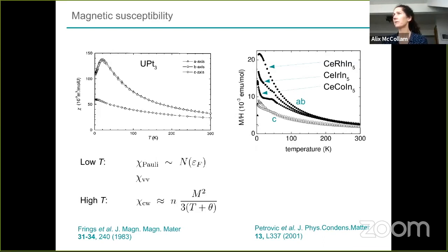Do you have cases where there are not Fermi liquids, but still you see de Haas-van Alphen? So many of the heavy fermion systems are not Fermi liquids. They have maybe T-linear or T to some other exponent resistivity and quite distinctive non-Fermi liquid Pauli behavior in the various quantities, but the de Haas-van Alphen effect seems to work one way or another. So in fact, you can just put whatever interaction you like really into the de Haas-van Alphen.